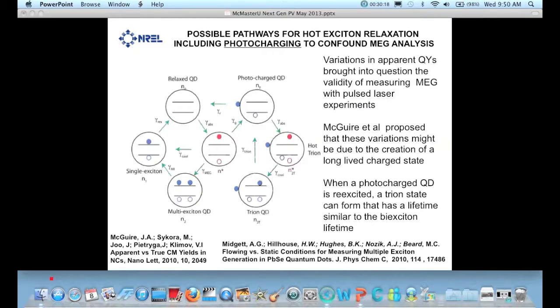So that's just shown here. When you start with a neutral dot, you excite it with a high-energy photon. You want this extra energy to produce 2 excitons, and then this will decay slowly, over maybe a nanosecond, by non-radiative recombination through surface states to a single exciton. But in some cases, this electron can be trapped at the surface, and then when the pulse comes in, it'll see a trion. It'll have an electron on the surface, and then you create another electron-hole pair, and this also undergoes a fast decay, which can confound the signal.